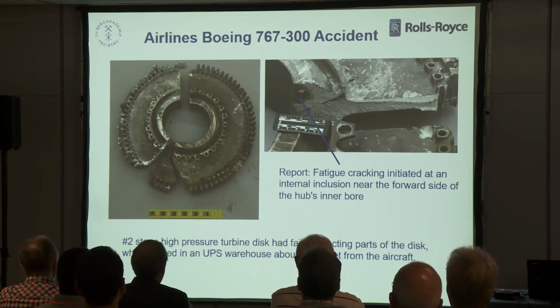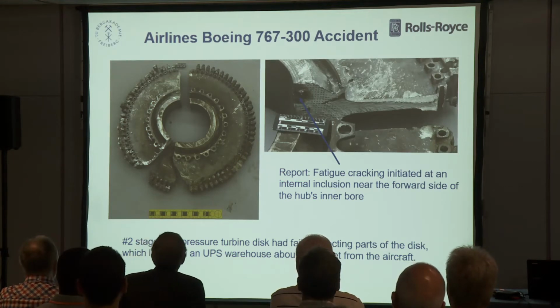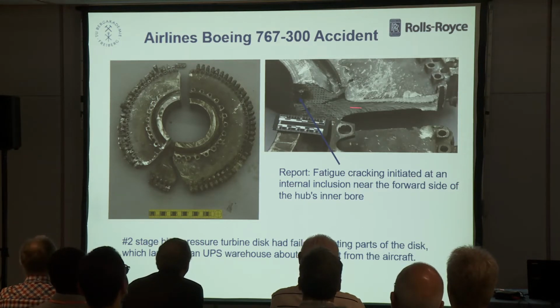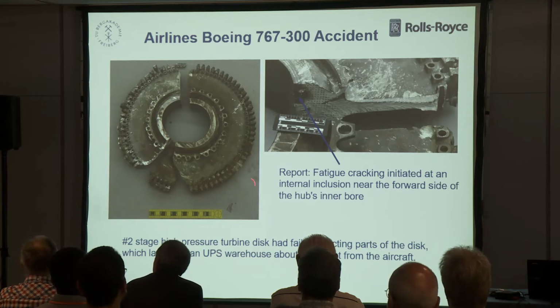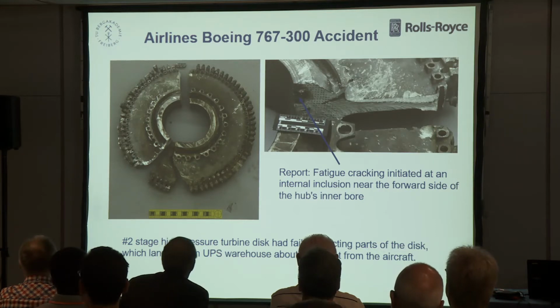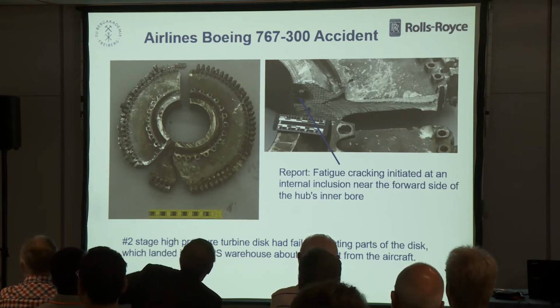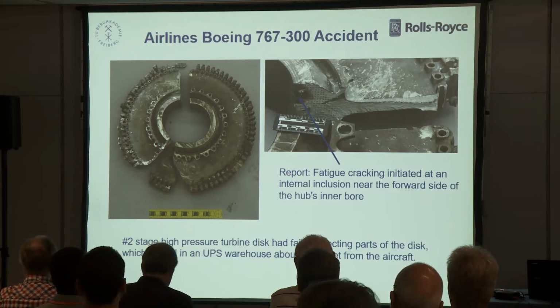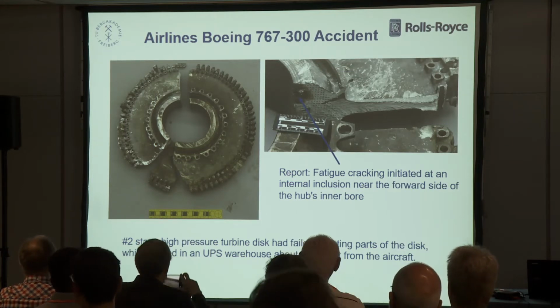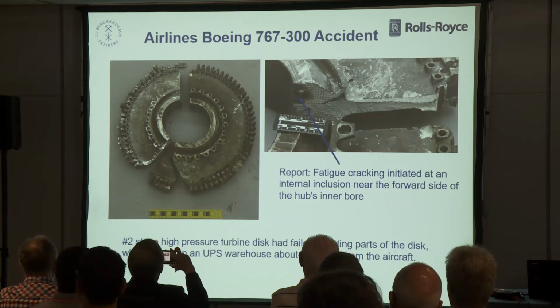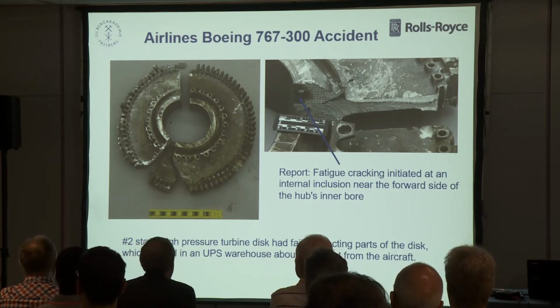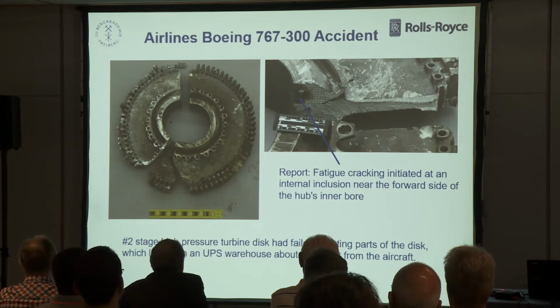So what was the reason? It was a failure of such a disc. It started as fatigue from a small internal inclusion here, growing up, and then there was a final fracture, and it broke into several pieces and had so much kinetic energy that parts of them flew away through the casing 1 kilometer away and landed in a UPS warehouse near the airport. And they destroyed the wing and not the fuselage, and so it started to burn.